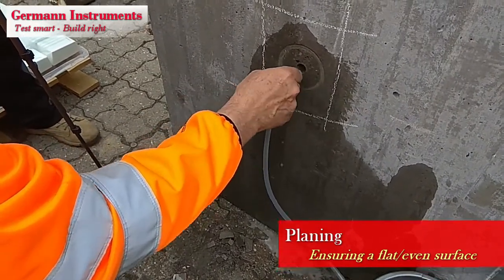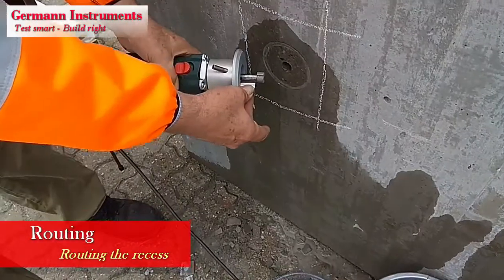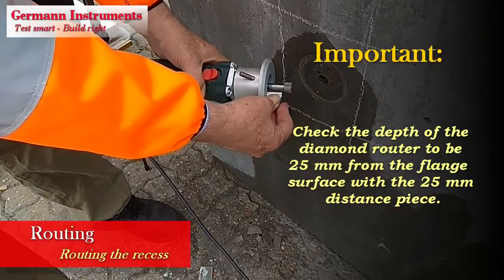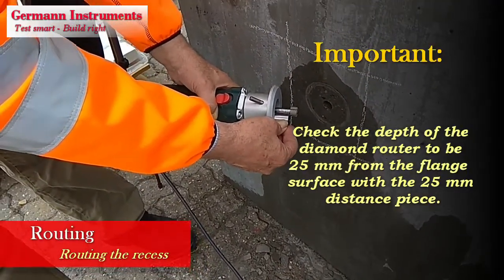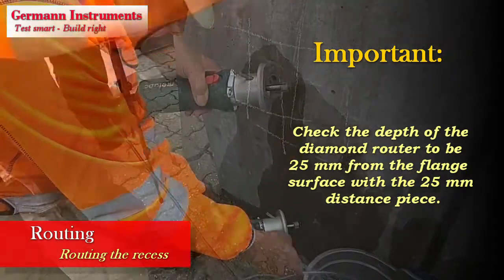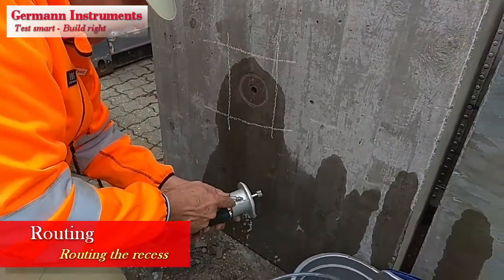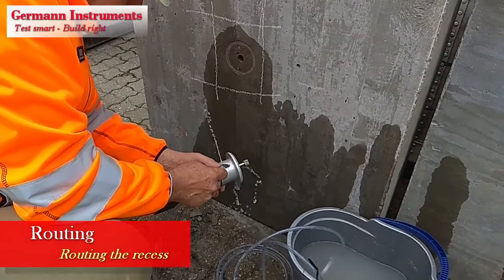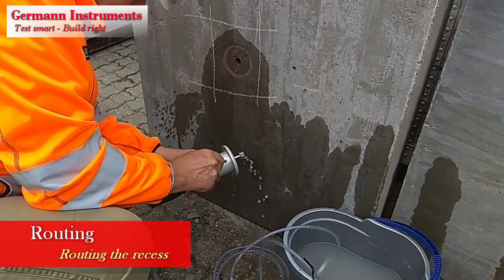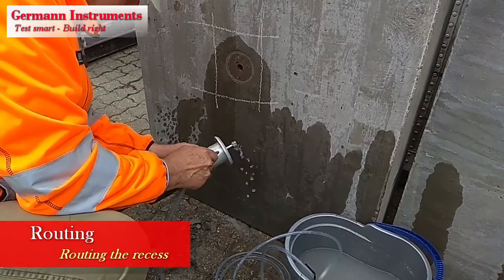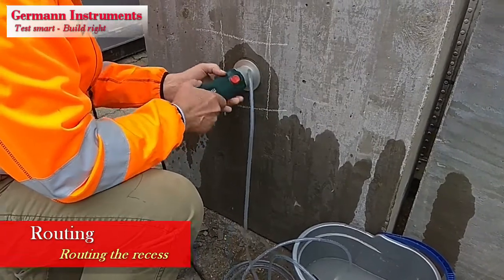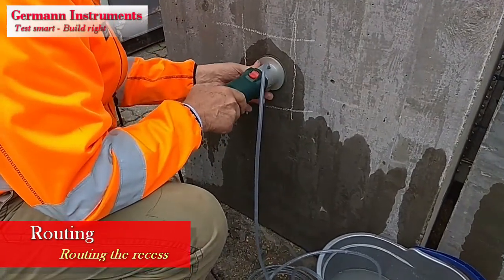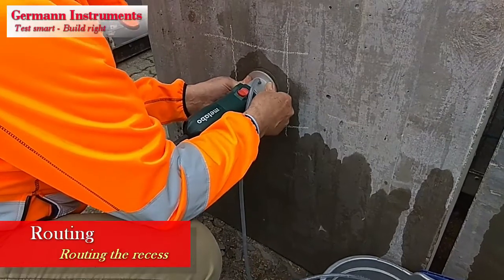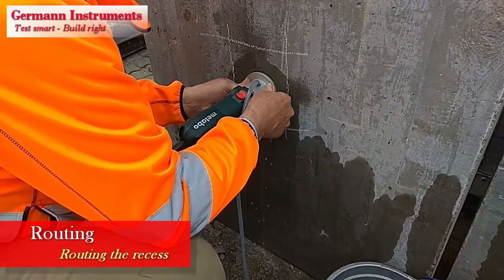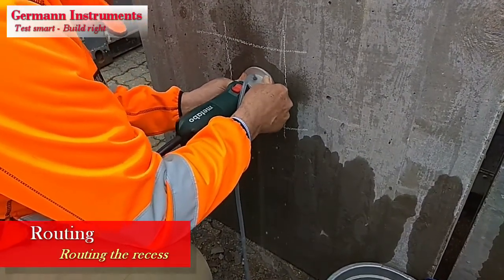The recess router is prepared. Check the depth to the diamond bit to be 25 mm from the flange using the 25 mm distance piece supplied in the preparation kit's tray. Connect the water supply and route the recess in bigger and bigger circles until the flange follows the planed surface outer 100 mm circumference. Press all the time the flange with 2 sets of fingers against the surface.